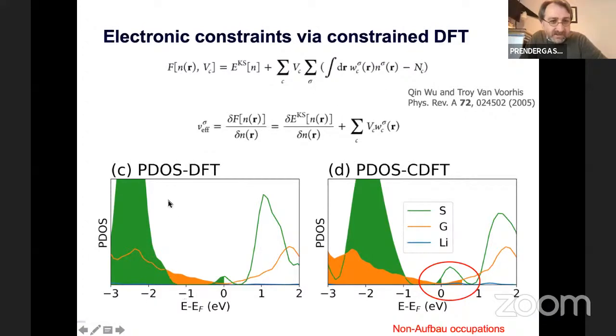And then the result is that if you just do regular DFT, you'll find that there's kind of a Fermi level pinning, right? Wherever the Fermi level is in the metal, you'll see that the surrounding dielectric will pin itself to that level. Instead, if we use this constrained DFT, which you see now is what I've labeled as non-Aufbau occupation. So the Aufbau principle says you should fill states, whatever states they are, up to the point where you run out of electrons in order of increasing energy. But in this case, you can see there are some empty states below some states at higher energy that are occupied. And that's enabled by using this constraint that shifts the local potential in different regions.